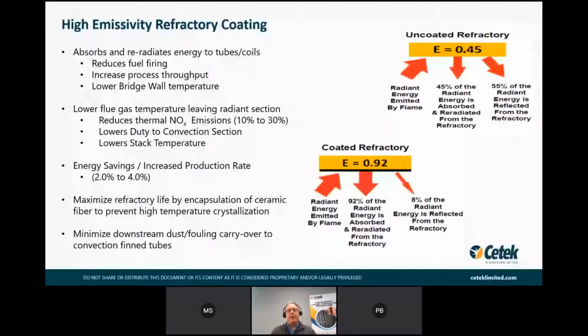Now, the beauty of the technology is if you're in the busy season and you need to kick up your production and you want to take advantage of the savings from the coatings, now you can do, let's say, 8% more barrels per day instead of on the savings side of it. So you can shift as your demands require year over year, and think about that over 2 turnaround cycles. A lot of flexibility from the coating itself and how you want to use it. So from our perspective, why wouldn't you maximize the radiant energy capture rather than simply letting it exit the stack?